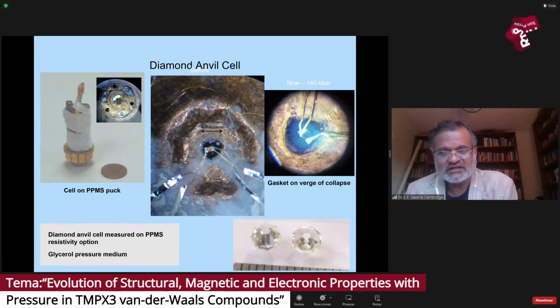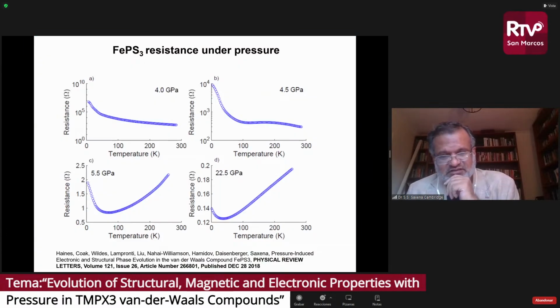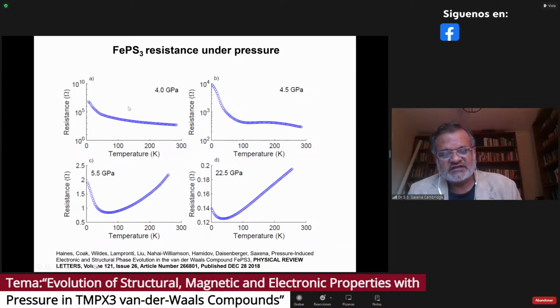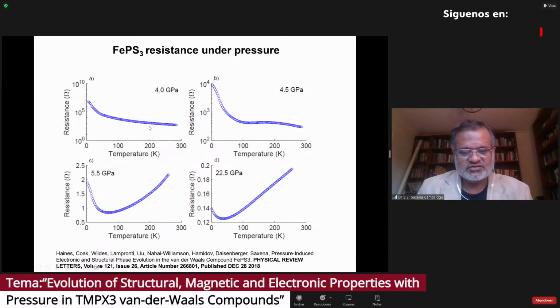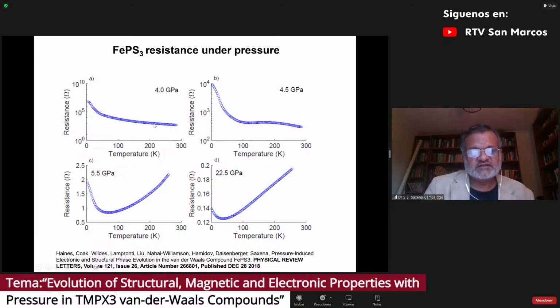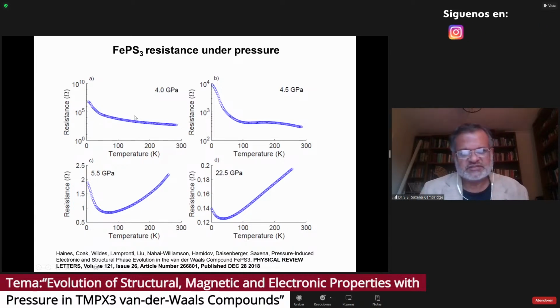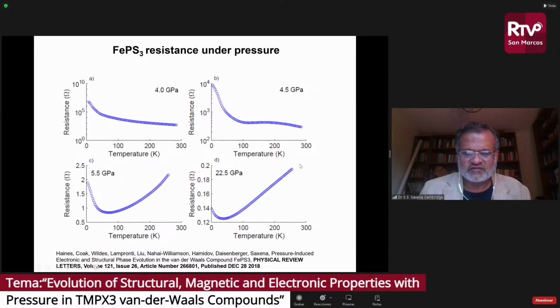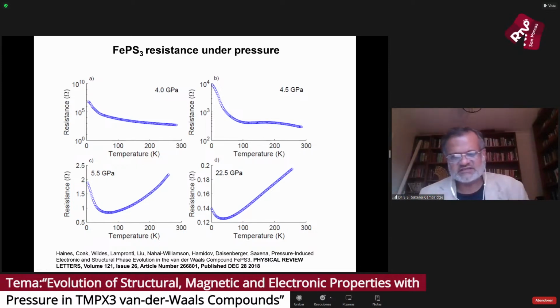I can talk more about it for those who are interested regarding the technique. But the initial results were very, very promising. So initially, this is an insulating part. We are first showing the data on FePS3, iron, phosphorus, sulfur 3, and we see resistance versus temperature data at different pressures here. What you see is that resistivity acts like a semiconductor or insulator at reasonable pressures. But then as you increase pressure, you start to see a change in how the curve looks, and eventually it starts to look reasonably metallic over a wide temperature range. But there's also something funny happening at low temperatures, an upturn that emerges, which is to be discussed as we go along.